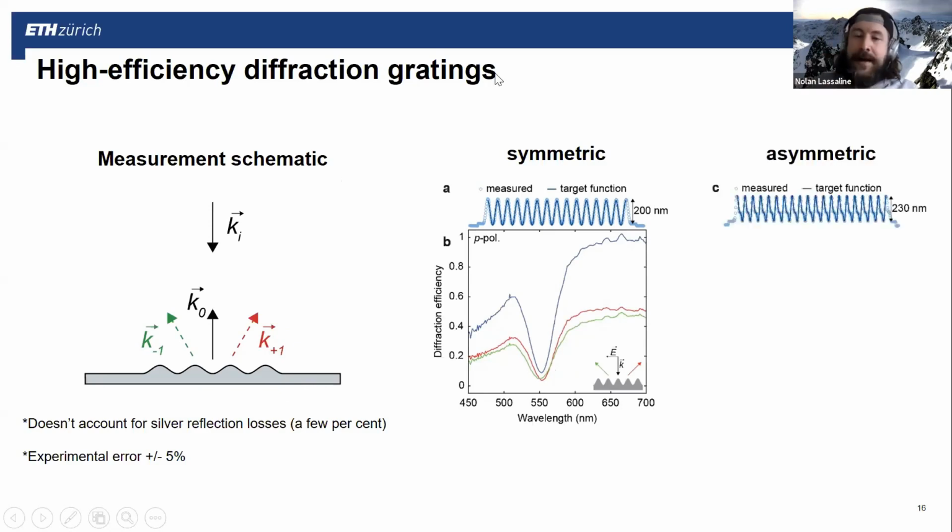And for those of you that know a bit about optics and gratings, people do this with these so-called blaze gratings. And a way that we can do this very simply with these sine waves is we can simply add an additional spatial frequency, so just 2 sine waves here. And if we choose the phase correctly between these two components, we can arrive at this asymmetric case here, which actually is somewhat of an approximation to a blaze grating, as we see here.